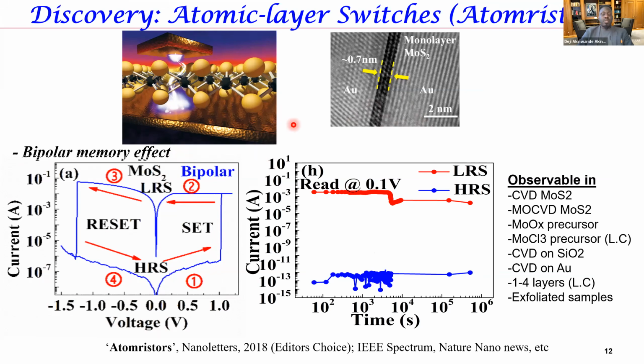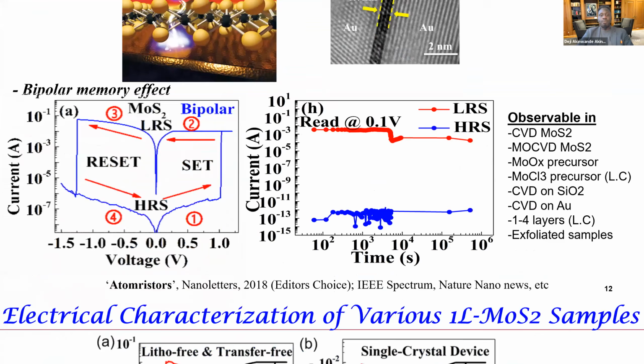So one of the criticisms we received in the early days, 4 or 5 years ago, was that since we were reporting this for the first time, there was a lot of suspicion that maybe this was an extraneous result, not intrinsic to the material. So we decided to get this MoS2 material from other experts that grow high quality materials. Basically, on this list is virtually every kind of MoS2 that can be produced, and we could conclude that this phenomenon exists in all of these materials. So we declare that this is an intrinsic effect of the material.